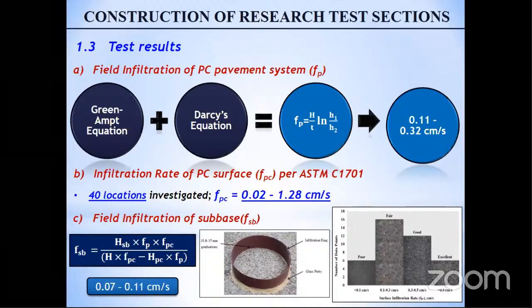Later, we did a surface infiltration rate test as per ASTM C1701, where about 40 locations on the entire stretch were selected and investigated. And it was observed that the surface infiltration rate varied somewhere from 0.02 to 1.28 centimeters per second. At the bottom of the screen, you can see there is an infiltration ring being sealed with glass putty over the surface of the pervious concrete pavement, and graduations were marked onto this ring. The whole intention was to maintain the head of water between 10 and 15 mm. Basically, the idea is to note down the amount of water and the time it takes to pass through the surface of the pervious concrete layer.